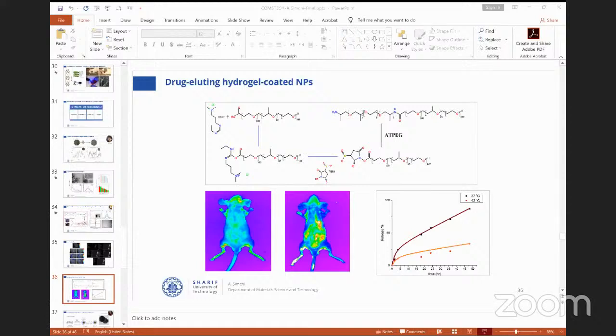Following that, we tried to modify the shell with better polymers to incorporate biomolecules. We used an amine-terminated PEG system to cover the surface of our hybrid nanomaterials, and then conjugated biomolecules on top of the amine-terminated PEG polymer and used it in vivo to treat cancerous tumors by three effects: not only the magnetic effect, but also light and also drug. So it speeds up killing the cancerous cells, and simultaneously we are able to image how the cells and tumors are removed.